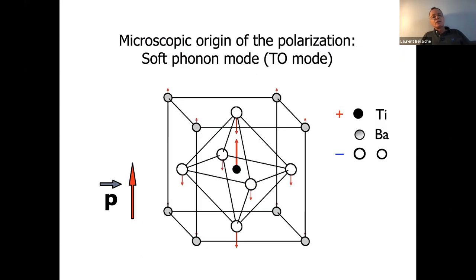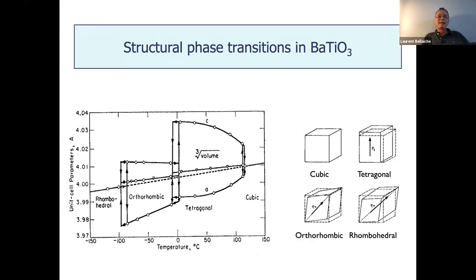As Osvaldo explained yesterday, most of the time the polarization comes from one single phonon mode. It's a TO mode, called the soft phonon mode. For example, in barium titanate, this is how it looks. Titanium is moving up, barium a little bit up as well, and oxygen ions are moving down. So it's a collective motion of ions. It's a gamma center mode, and this creates the polarization in barium titanate.